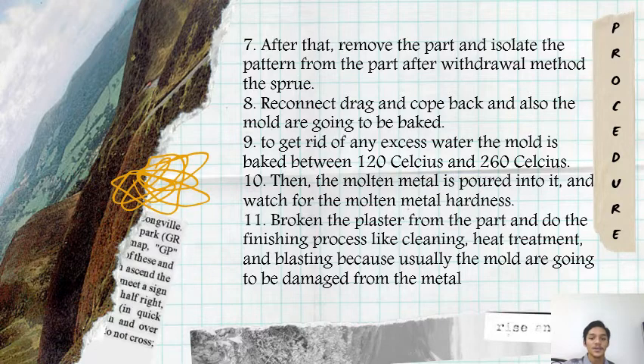Number 8. Reconnect the drag and cope back, and then the mold is going to be baked. 9. To get rid of any excess water, the mold is baked between 120 Celsius and 260 Celsius. Number 10. Then the molten metal is poured into it, and watch for the molten metal to harden. Last, break the plaster from the part and do the finishing process like cleaning, heat treatment and blasting, because usually the mold is going to be damaged by the metal.